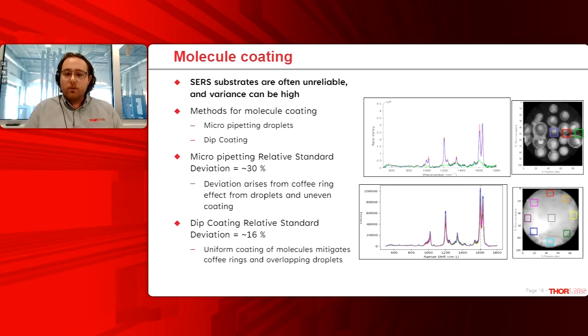And when we do that to our wafer and we measure across the entire wafer, we see that there are some coffee ring effects, there's some overlapping of droplets, and overall you get this very non-uniform coating across the entire surface. And when we measure the relative standard deviation of those areas, we see that the RSD value is around 30%. So this is not really acceptable for many applications. However, if we perform something called a dip coating procedure, where we take the entire wafer and we submerge it in a bath of these molecules, we can then let it incubate and let the molecules bind to the surface and rinse away any excess molecules. We can then take our measurements again across the entire wafer, and we see a much more uniform response. Our relative standard deviation dropped to around 16%, which is quite good for these SERS substrates.